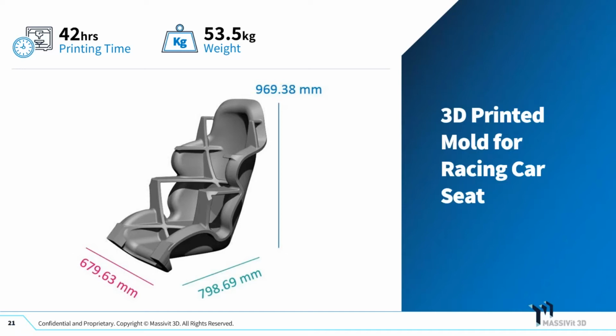So typically, after the print, regardless of the size of the part, it's going to take 10 hours to post-cure to get the mold material to ideal mechanical properties. And then it takes somewhere around 24 to 30 hours to remove the shell. You just put it in a tank of water. There's no chemistry, there's no caustic chemicals that are breaking down the shell material. It's just tap water. There's no heat, there's no agitation.